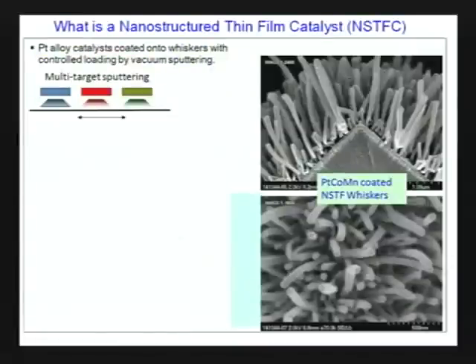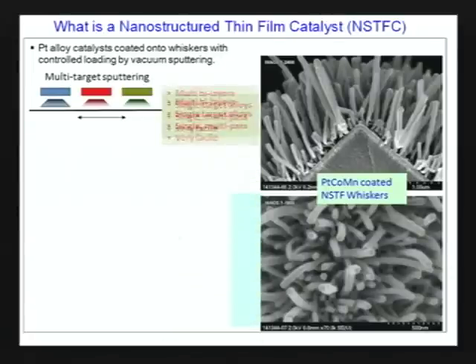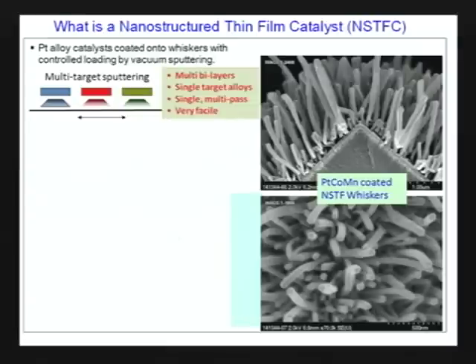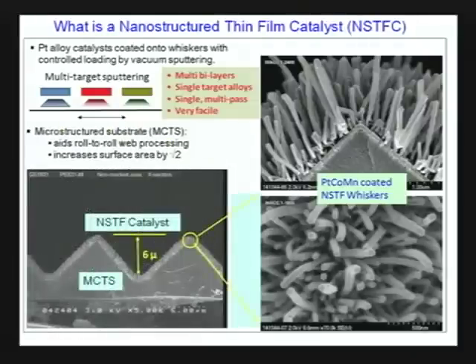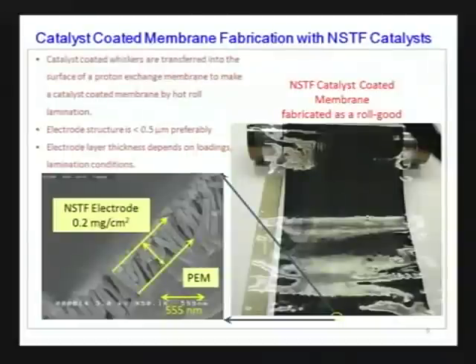We coat those whiskers then with catalyst, and it completely surrounds the perylene core, this crystalline whisker core, with the polycrystalline catalyst film. And we use sputtering, which is a very flexible and high volume compatible process for applying the catalyst. You'll also notice, of course, that we apply these to a microstructured substrate, which is based on 3M core technology as well, for 2 reasons. One, it enables us to do the roll-to-roll processing, and secondly, it gives us another 40% increase in surface area.